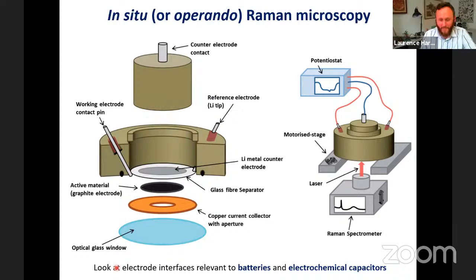Yep. I mean, you're absolutely right. That's true. You really want to be looking at the front-facing part of the electrode. I think one of the challenges is to not have too thick of an electrolyte layer you're measuring through, which can interfere with some of the key bands that you're looking at. So this backside configuration is a messy compromise between being able to get the spectra. I would say the electrode is fairly thin. It's a porous electrode, soaked in the electrolyte, and generally we don't see too much hysteresis between the electrochemical response and the spectroscopic response if we do scan slowly.